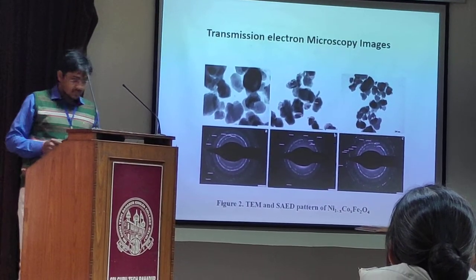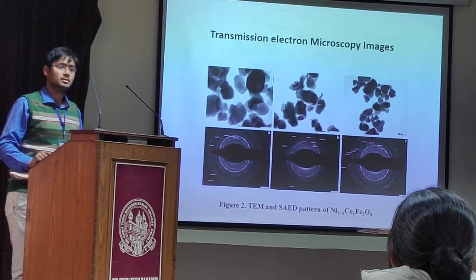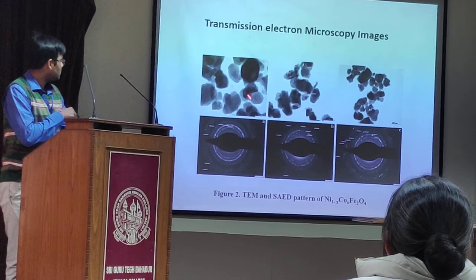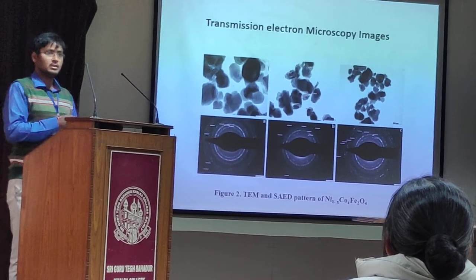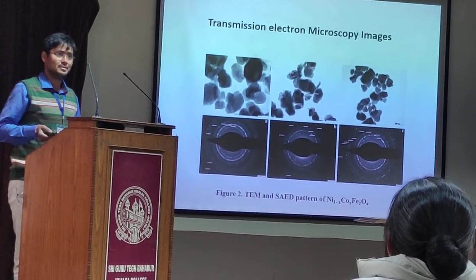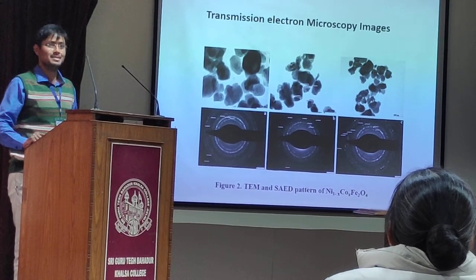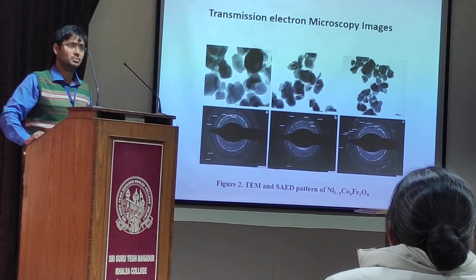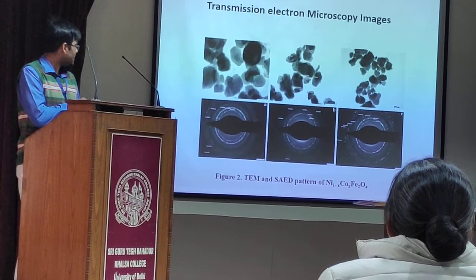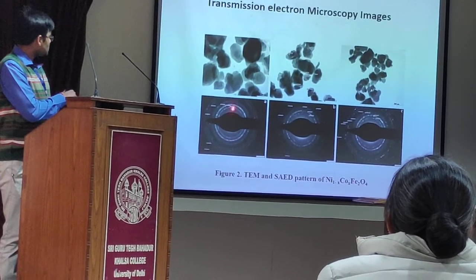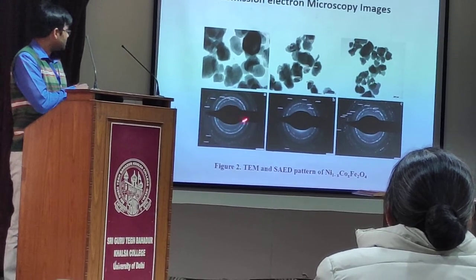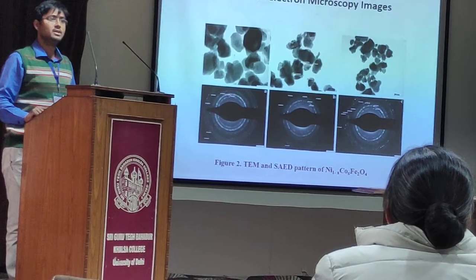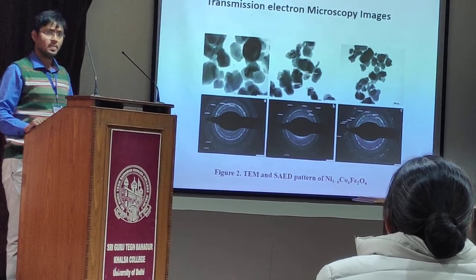I sent my material to IIT Powai for transmission electron microscopy. I obtained particle sizes of around 50 nm and 40 nm, with an average size of 40 to 50 nm. This is the SAED pattern showing a ring-dot pattern, indicating the material is crystalline in nature, which is in very good agreement with the XRD data.